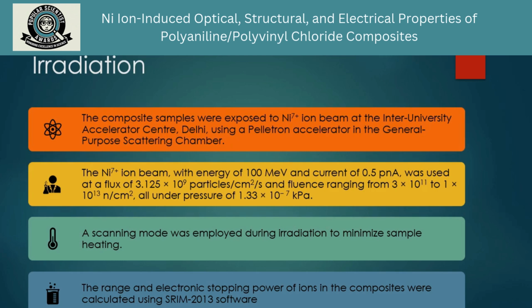Then the next process was the irradiation. The composite samples were exposed to nickel 7 plus ion beam at the Inter-University Accelerator Center, Delhi, using a Pelletron accelerator in the general purpose scattering chamber. The nickel 7 plus ion beam with the energy 100 MeV and current 0.5 pnA was used at a flux